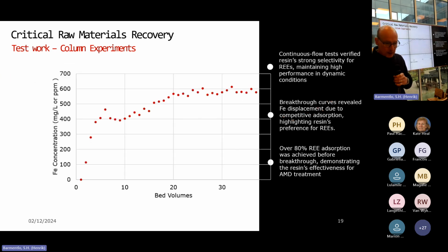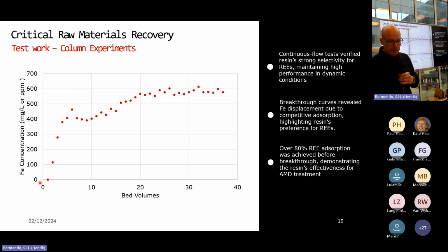But what we then did was we expanded this on the iron. And this is quite an interesting graph. The reason this one's interesting is it tells you that after a short space of time, you start seeing breakthrough, but we weren't seeing this immediate tapering off behavior, this plateau. And what that's telling us, and this is really cool for us, is that as your rare earths carry on absorbing, they start to displace the iron that's absorbed onto the resin. So this is why you're seeing this increasing behavior with time.